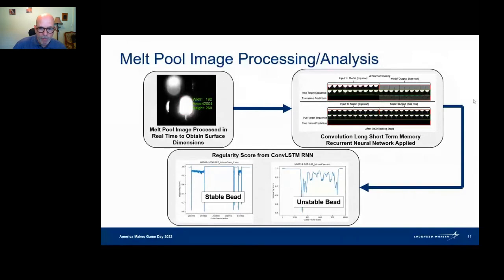With our image cameras, we were able to capture the melt pool image and to process the melt pool characteristics of width, total area, and length of that melt pool surface area, and able to do that in real time. What you see in this image is the actual melt pool. This is a reflection that's not part of our overall calculations. And so we were able to process this real time, and this allowed us to close the loop on the control system itself, so that now by specifying a set melt pool area and a targeted laser power condition, we could then control the laser power to maintain this melt pool area.